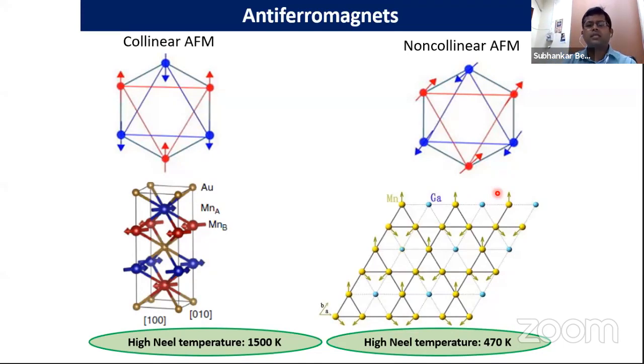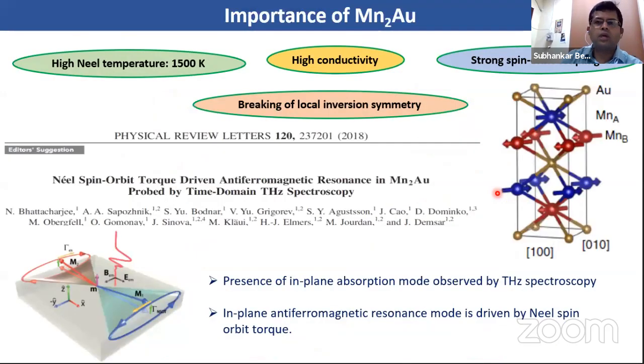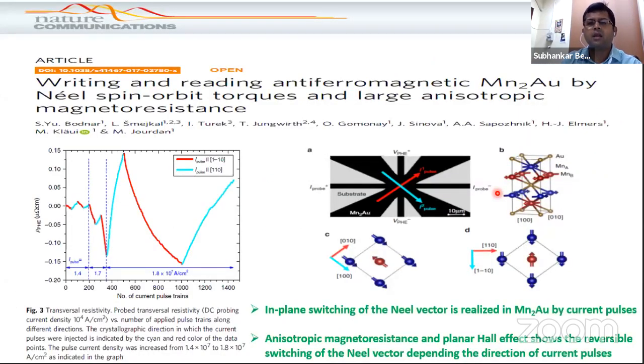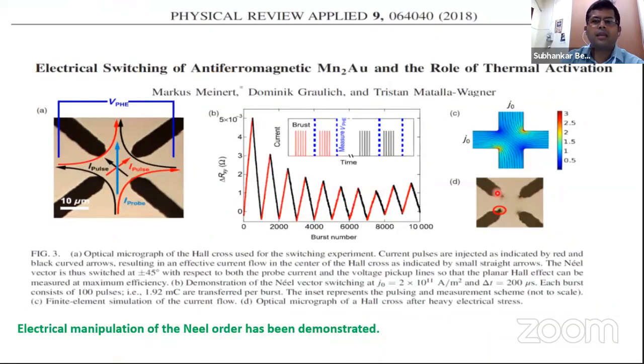And antiferromagnets you can broadly classify into collinear and non-collinear antiferromagnets. Collinear ones are like manganese gold, iridium manganese, nickel manganese, and so on. Non-collinear, there are iridium manganese 3, manganese gallium, and Mn3Ga. So manganese gold is a very interesting new antiferromagnetic system, which has a very high Néel temperature. And recently it has been shown that you can actually control the Néel spin orbit torque. I'm not going into detail. This is an electrical control of the Néel spin orbit torque, and so on.